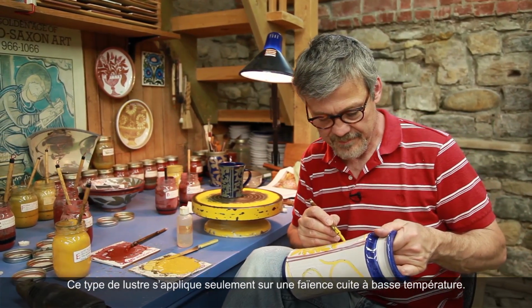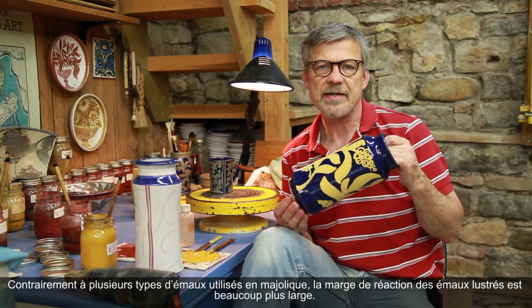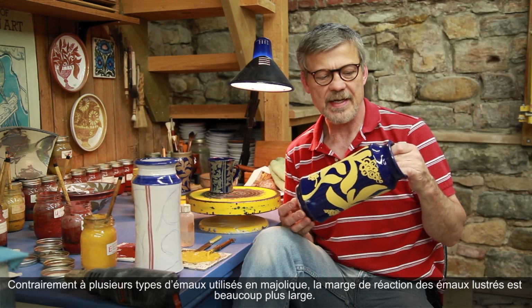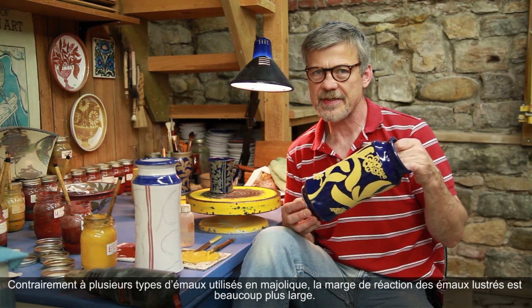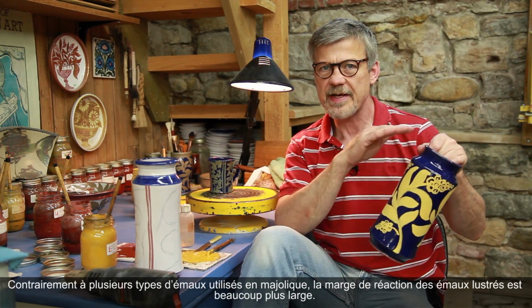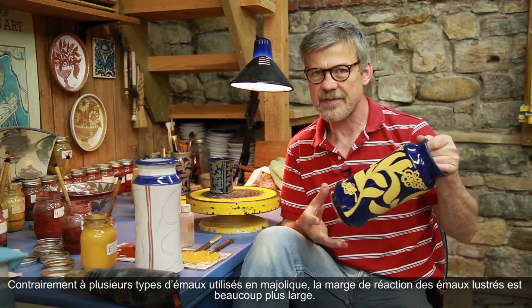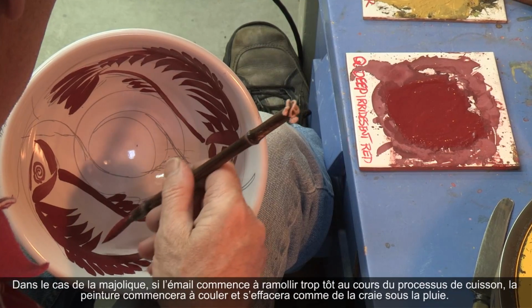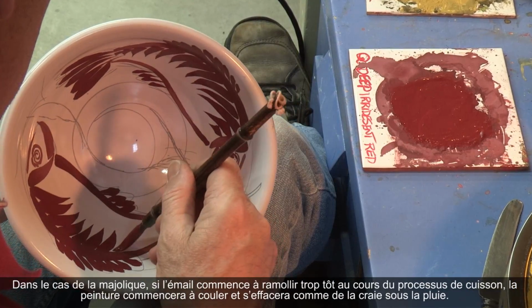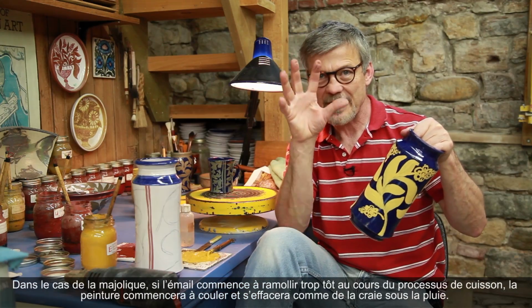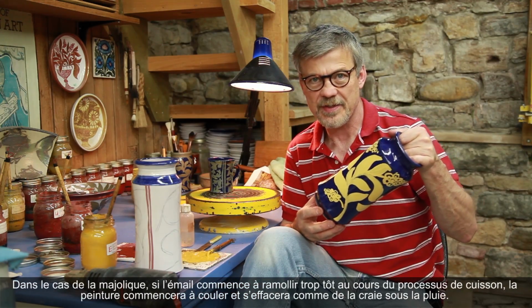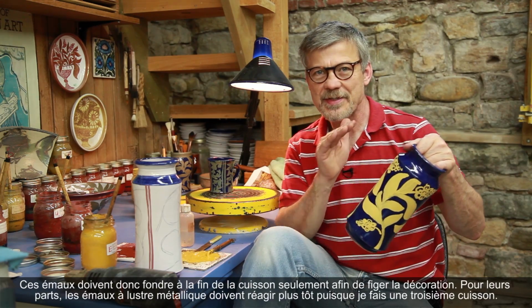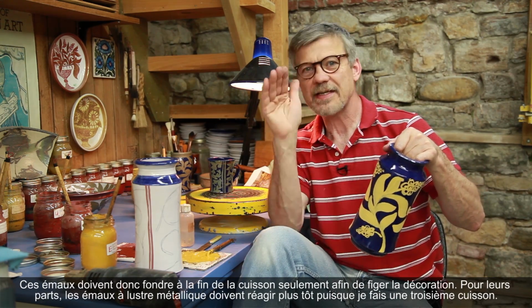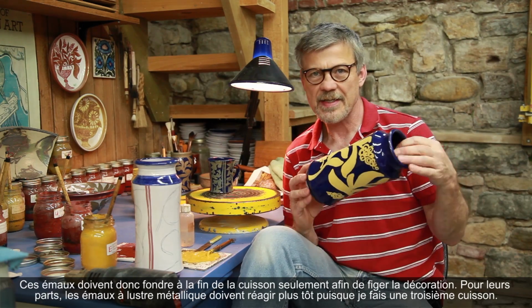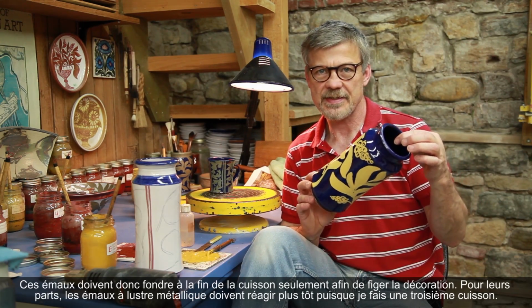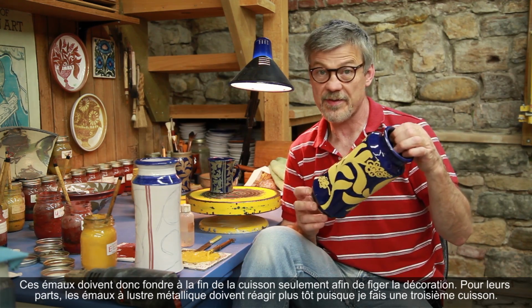So it's a lower temperature piece, but unlike lots of Maiolica type glazes, a glaze for luster is designed a little bit differently so that it has a much broader range at which the glaze starts to soften. If you made a glaze that softened very early in the process for highly painted Maiolica, all your beautiful painting would start to run like a chalk drawing on a rainy day. So those glazes are designed to sort of melt just at the end and freeze and hold the painting. Whereas these glazes are designed to yield to the process early because I'm doing a third firing.